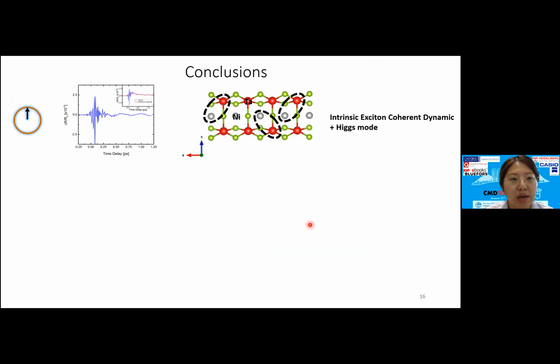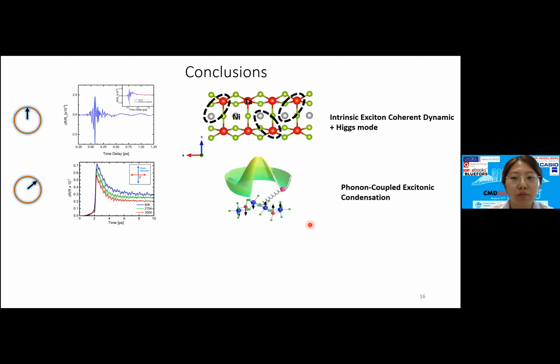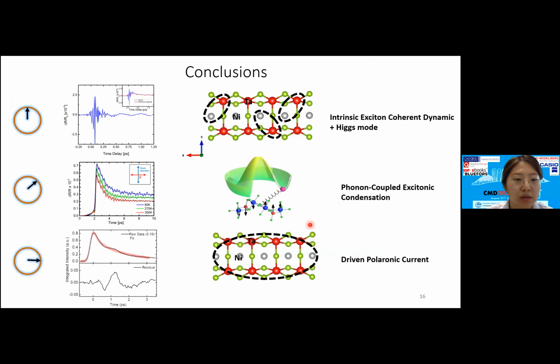So I'm going to summarize my talk. I've shown you that with a very short laser pulse we see the intrinsic excitonic current dynamics and Higgs-equivalent mode. With a longer timescale pulse, we saw the phonon-coupled excitonic condensation. And finally, we saw the dynamics of the gap. The collective excitations of the gap dynamics show not only the phonon-coupled excitonic condensation, the one terahertz phonon mode, but also this driven polaronic current, which is also observed in the terahertz range. So this is all of my talk, and thank you for the attention.